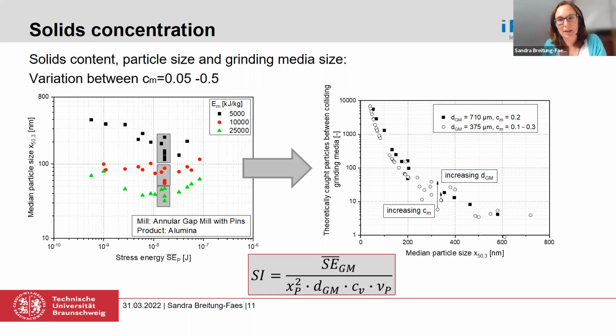On the other hand side, for the smaller grinding beads, here the circles, the concentration was varied in a range between 0.1 and 0.3. The curve in the middle is 0.2 as solids concentration, and the data points below are 0.1, and the ones above the curve are 0.3. And you can see how big the influence on the theoretically caught particles is when you increase the solids concentration. On the other hand side, for 0.2, I changed the grinding media diameter as well. And when you compare the black data points here with the circle where the small arrow is at, you can see that the influence is not that big. But all these three parameters have to be included into the model.